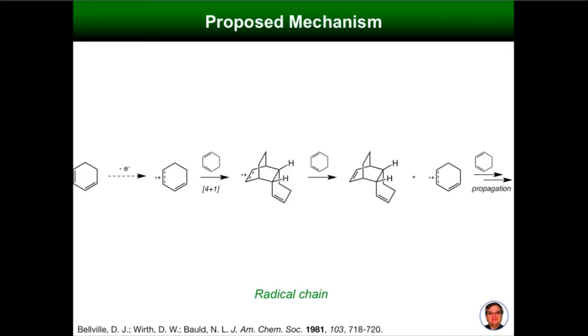The proposed mechanism involves taking an electron off of the diene, generating a radical cation species. This radical cation species can react with another equivalent, making this radical cation, which can lose the electron to cyclohexadiene again and undergo a radical chain process to make product. And so the initiation step may well be uphill, but the overall reaction can be downhill.